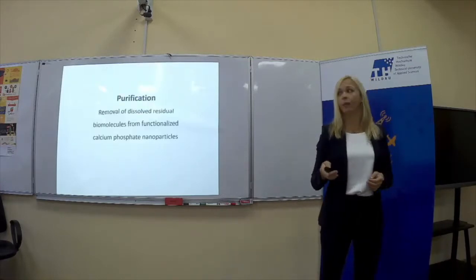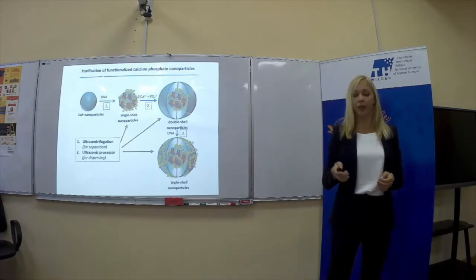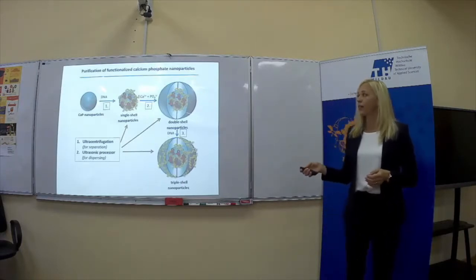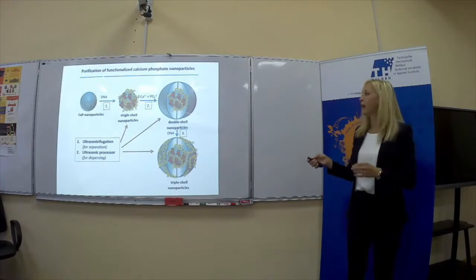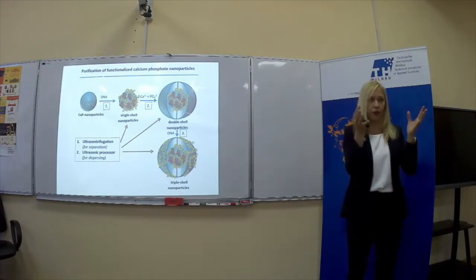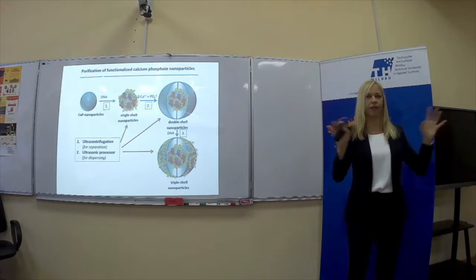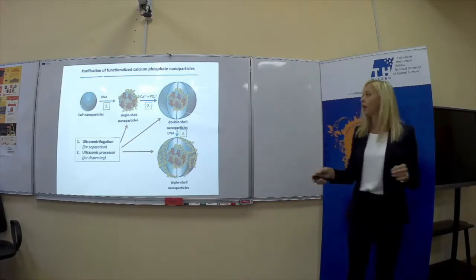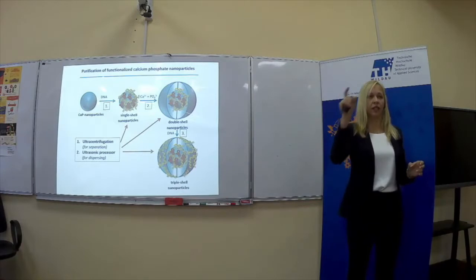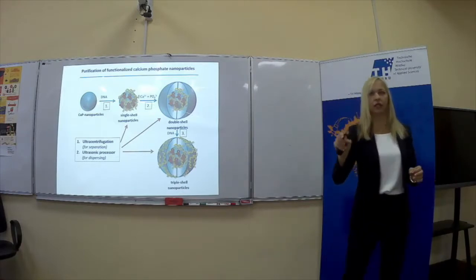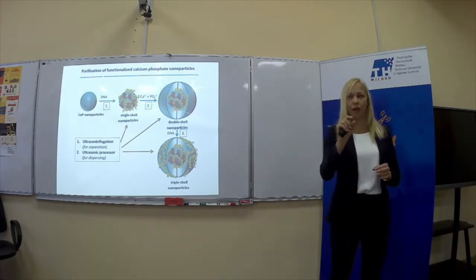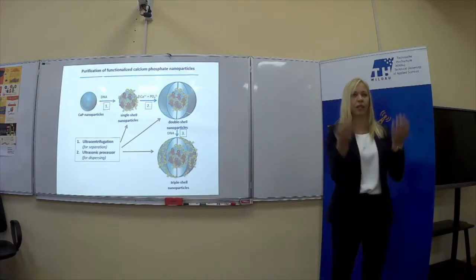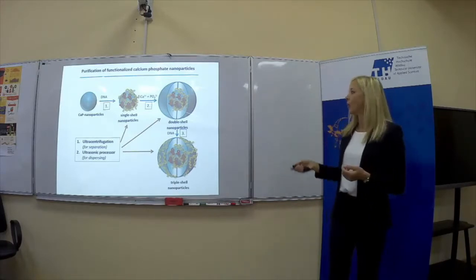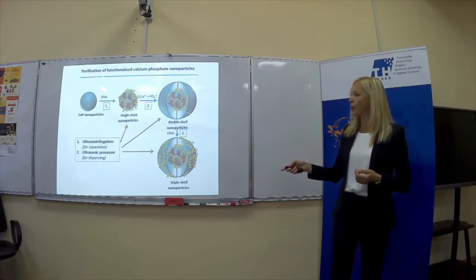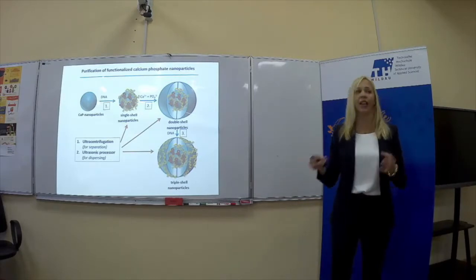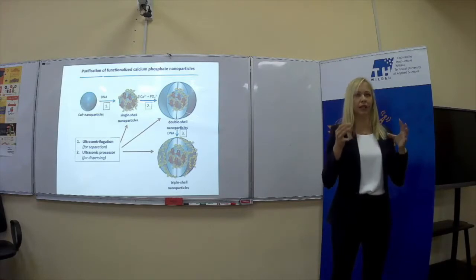Purification. Purification is very important. How do we usually do it? As soon as we mix the calcium phosphate, the first particles, we add biomolecules. We have the first shell, but imagine we still have free biomolecules in the solution. After this step, we centrifuge, do ultracentrifugation, and we can collect our nanoparticles, but the free molecules will be discarded. And so after each step, you do centrifugation and also ultracentrifugation.